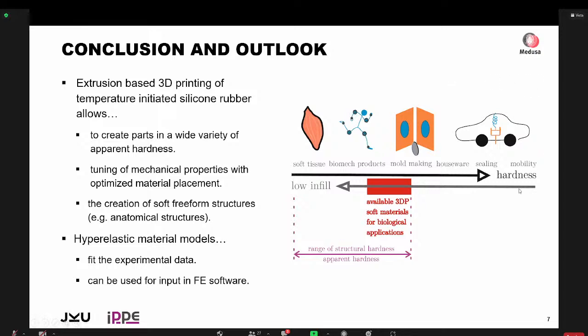Basically, what we would like to show with this paper is that normally you have to select the silicone specifically for your application. So the Shore value has to fit the application, because with molding, you can only produce 100% filled models. But with 3D printing of these silicone elastomers, you can actually produce a foam-like behavior, and you can use this Shore 50A, for example, for Shore hardness values down to 0. So this is very beneficial for us.